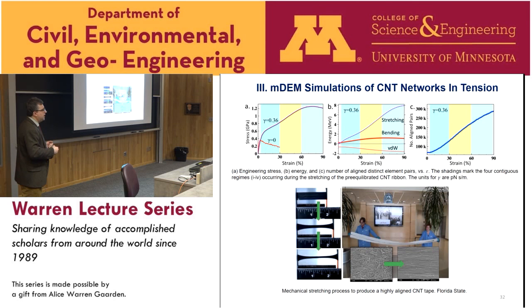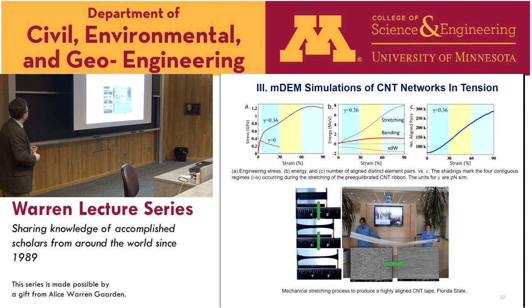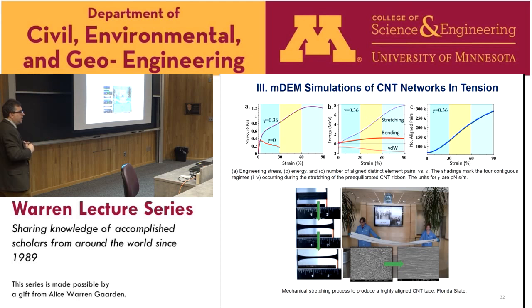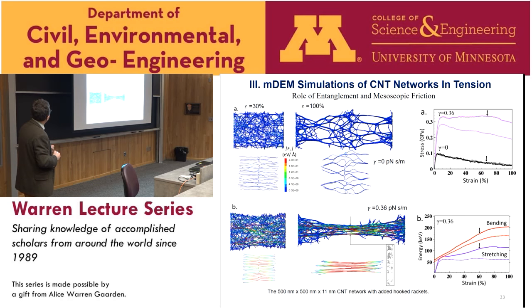What helps alignment? Viscous friction is a key element. This hardening, and essentially everything that increases load transfer, helps alignment in the structure. The waviness removal also helps — if we have tubes beyond a certain length and we remove this waviness while benefiting from entanglement, that increases load transfer and directs the zipping relaxation along the applied strain direction. Without this load transfer, the zipping relaxation simply does not happen.